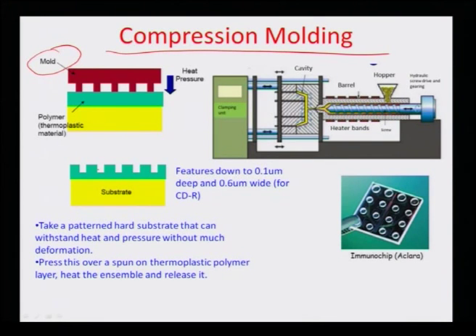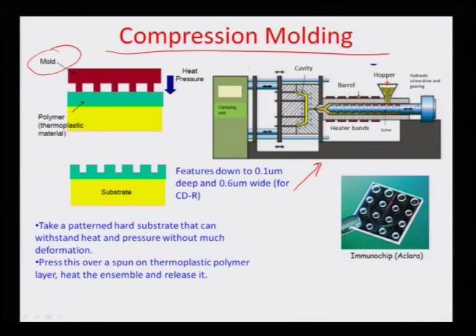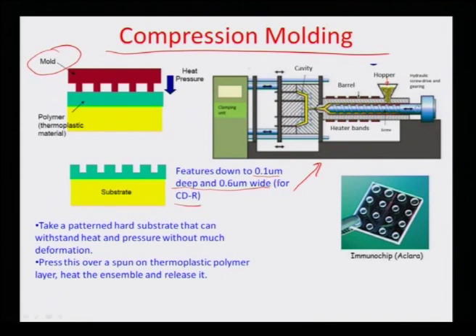Another very interesting process is injection molding. The feed of polymeric material happens through a lead screw which pushes the polymer melt. Heater bands melt the polymer, and the polymer melt is pushed forward into a die cavity with release agents on both sides. When the polymer melt enters this low temperature zone it immediately solidifies and takes the shape of the die. These techniques are used today for creating CD-ROMs with features down to 0.1 microns deep and 0.6 microns wide.